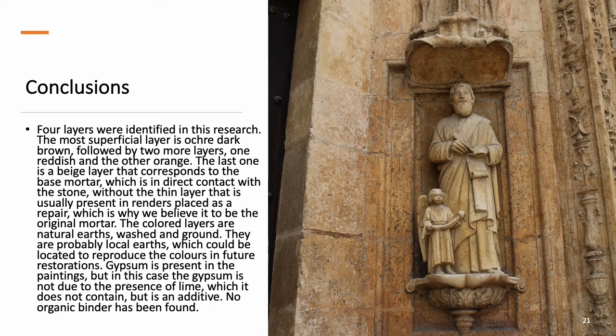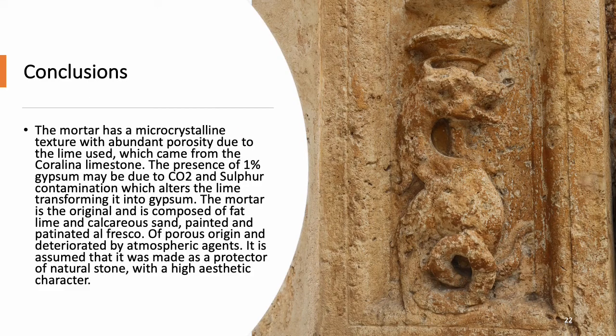Gypsum is present in the paintings, but the gypsum is not due to the presence of lime, which does not contain it, but it is an additive, no organic binder has been found. The mortar has a microcrystalline texture, with abundant porosity due to the lime used, which came from the Coralina limestone. The presence of 1% gypsum may be due to the CO2 and sulfur contamination, which alters the lime transformation into gypsum. The mortar is the original and composed of fat lime and calcareous sand, painted and patinated al fresco.